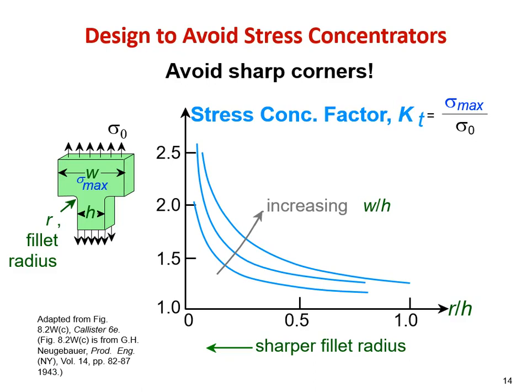And in fact, for a very small radius to lower section thickness, we're going to walk up those curves, decrease the value of our x-axis, and get up into a very steep part of the curve. So from this, the better way to drop that stress concentration factor is to really increase R, the fillet radius, in the case of this particular geometry. So again, two different ways to change your stress concentration factor.